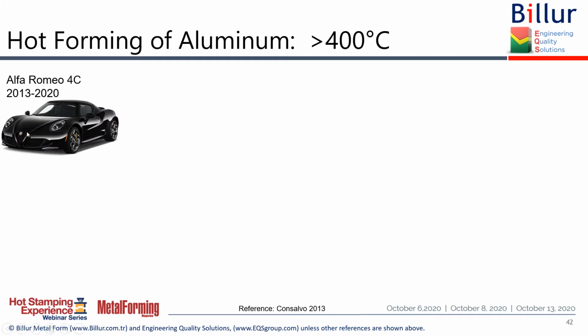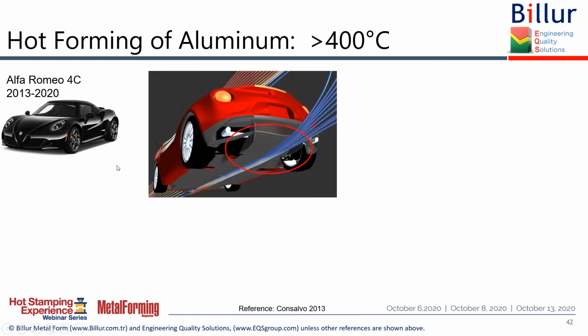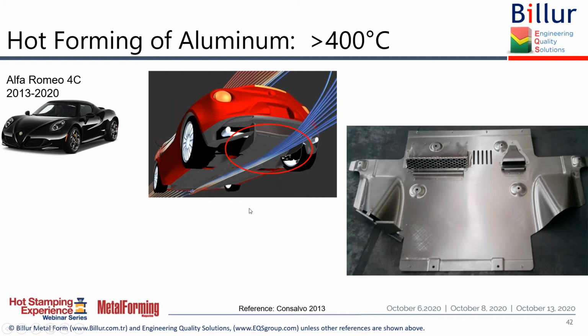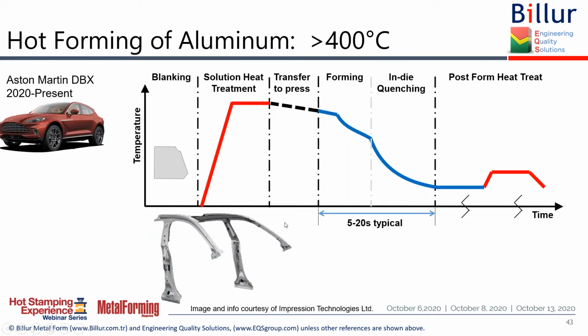Another hot forming application was in a very low volume car, Alfa Romeo 4C, and you would see this floor panel that was formed from 1.5 millimeter, and it was formed at 450 Celsius in a PHS line. Another very recent hot forming application is from Aston Martin. In fact, in DB11 that was rolled 2 or 3 years ago, only the A pillars were hot formed aluminum. Now in the DBX, there are a total of 9 components, A, B pillars, and roof rails done by 6082 T6.